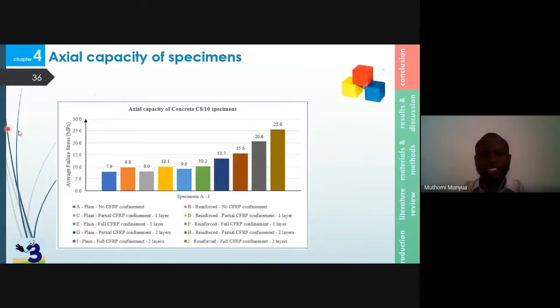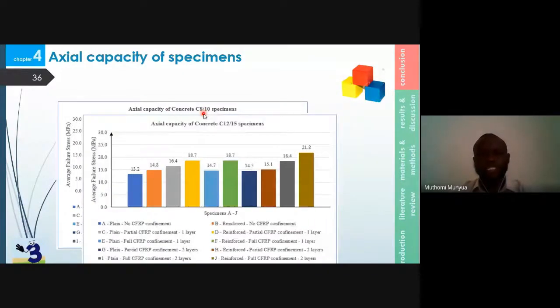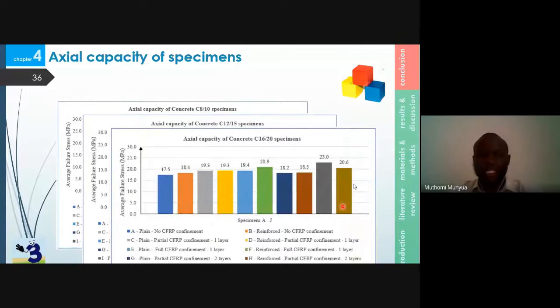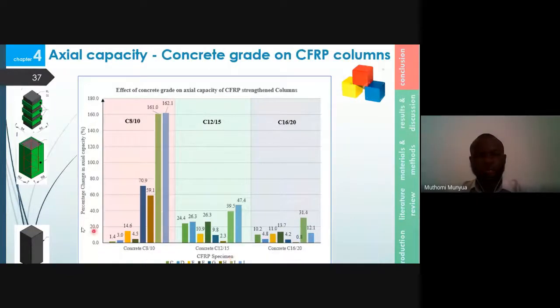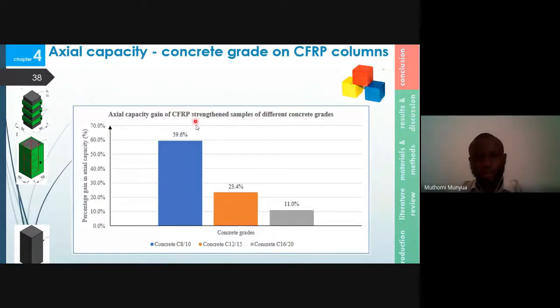The axial capacity was represented in bar graphs. In this case, C810 concrete, C1215, C1620, and the last 8 specimens, C to J, were compared with the controls A and B. We found bar graphs where C to J are compared, and this was the trend. To make this clearer, the averages were taken, and it was found that the weaker the concrete, the higher the effect of CFRP.